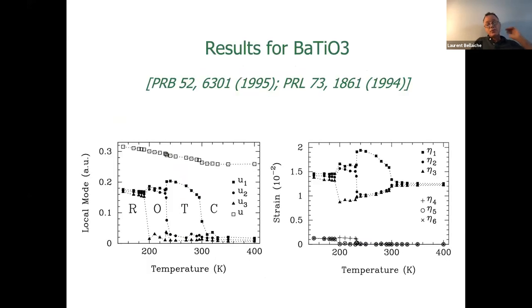And for example, this was the first result in this famous paper of Zhong, Vanderbilt, and Rabe. This was for barium titanate. On the left side, this is local modes versus temperature. This means polarization. On the right side, it's the strain versus temperature. What can you see? You reproduce the experimental phase transition sequence. You go from cubic, then tetragonal, for which polarization is along 0, 0, 1, then orthorhombic, and then rhombohedral, for which now polarization is along 1, 1, 1. And along these changes in polarization direction, you see that the strain is changing as well.